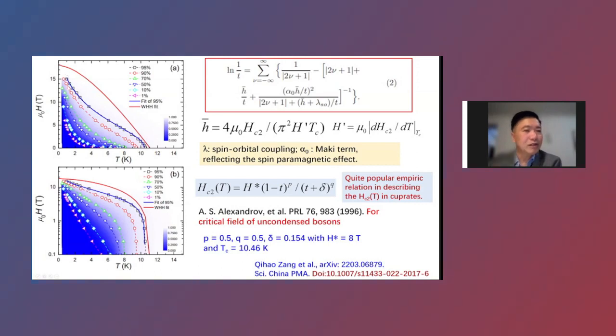Actually, this behavior has been found in many other systems, such as Thallium-2201 and YBCO by different groups. Then we noticed one paper by Alexandrov et al. It says that for the critical field of uncondensed bosons, which means that this is not a real upper critical field, it is for the condensation temperature and field. It gives some kind of theory, and following the theory, we put forward this kind of empirical relation for the upper critical field.